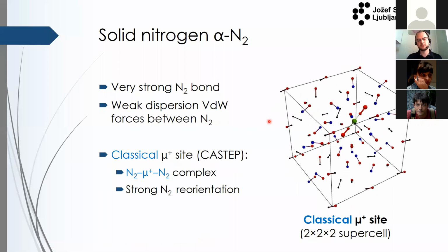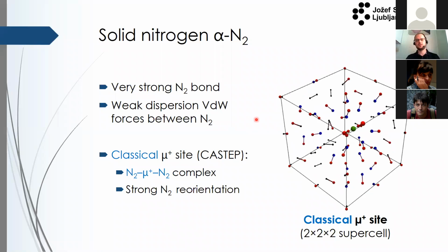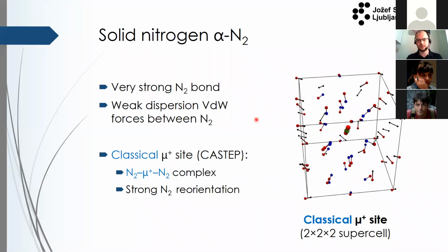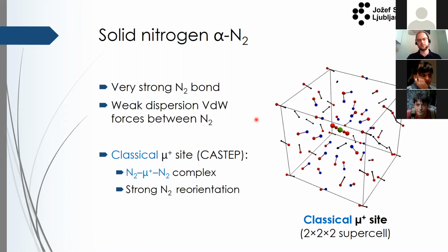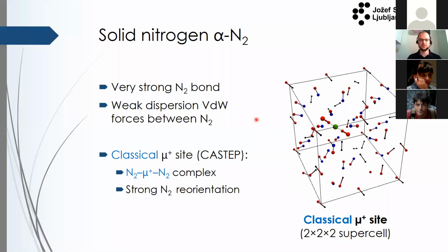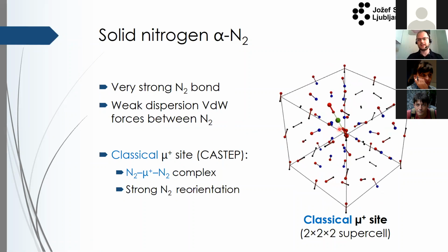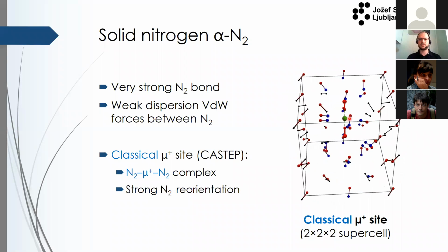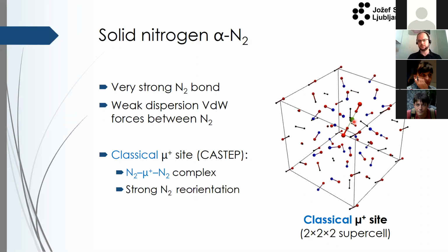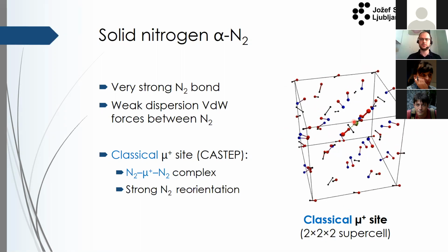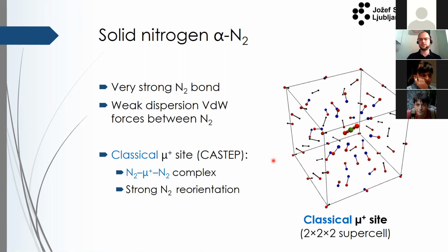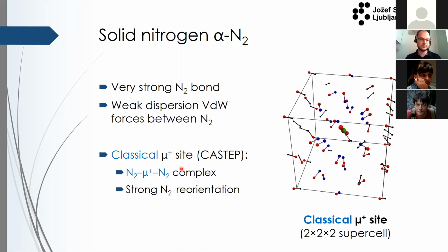So I started with this crystal, and if we put a muon inside here, a muon in this case is a positive particle. So we're working with antimatter actually. So it's an anti-muon technically. So it's a positive muon that we implant in there, and it acts like a lighter isotope of hydrogen, of ionized hydrogen, I guess. From the point of DFT, there's no difference in the external Coulomb potential if it's a hydrogen, a deuterium, or a muon that's producing it.